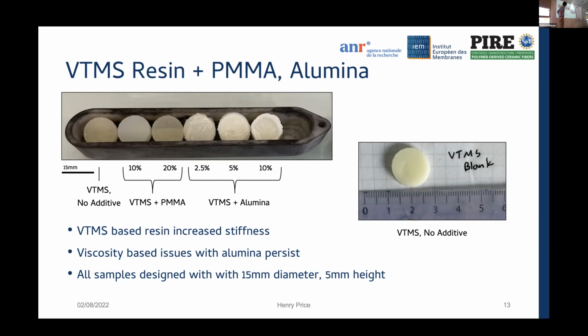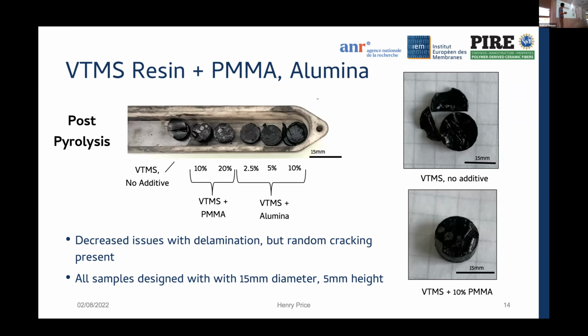So now, post-pyrolysis, the delamination issues were less prevalent in this VTMS-based resin. And I believe it's because of what I mentioned previously at the beginning, which was the increased cross-linking caused by the resin chemistry here.